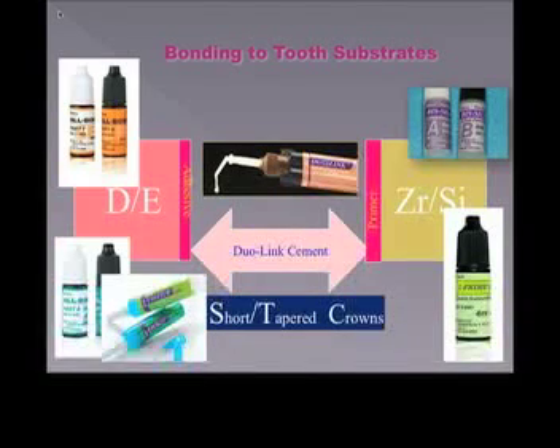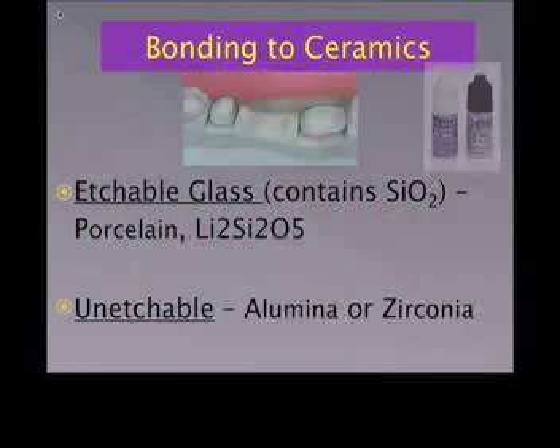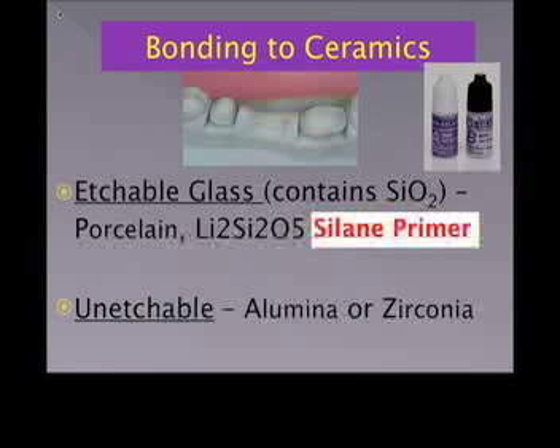Bonding to dentin or enamel substrates is a clinically driven decision, but bonding to ceramic indirect substrates is a research-driven requirement. Glass oxide containing substrates contain an etchable and amorphous glass phase; hydrofluoric etch or silane primer is the standard of care. But metal oxides are crystalline in nature and require primers having specific chemical strengths—silane is ineffective on metal oxides.